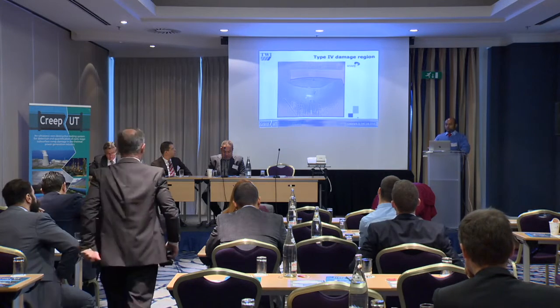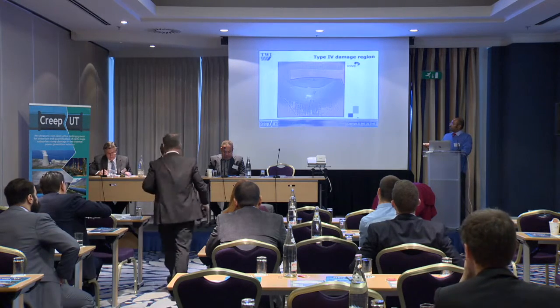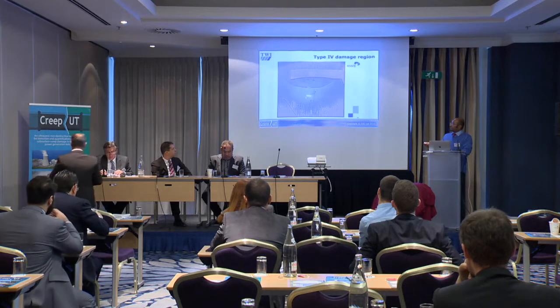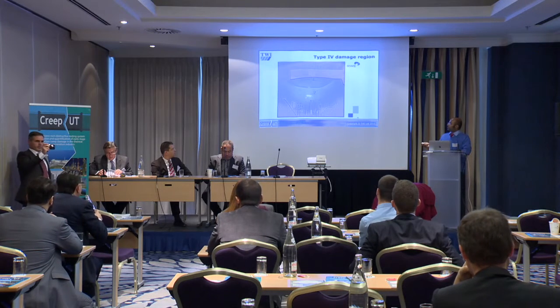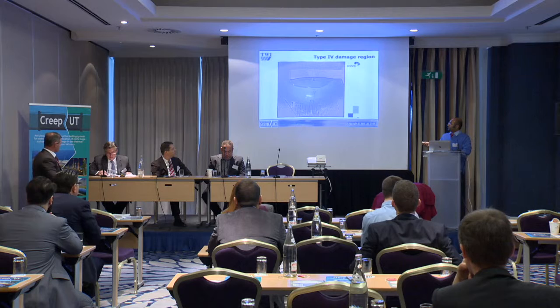So this is an image of an actual crack that was found. It was not the component that we were given to work on, but it was another component from the same header system, and you can clearly see that there is a cracking that has appeared on the surface.